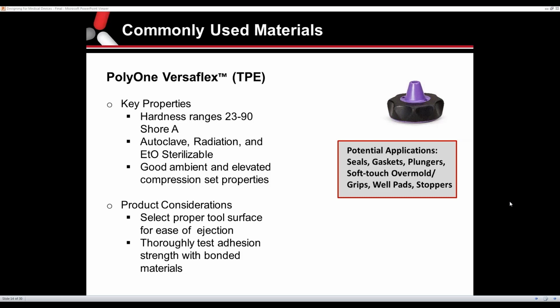The considerations that you want to think about with this material, and I know John and Glenn are going to have some more to add from the processing standpoint, but it's really important that you consider proper tool surface, and I'll let you guys talk about that in just a second. But also, if you're looking at this material as an overmold, make sure you do testing, or that the material supplier helps you do testing on adhesion. This particular material has really good bond strength, but you need to consider what material you're overmolding over, and that you have the bond strength that you need.